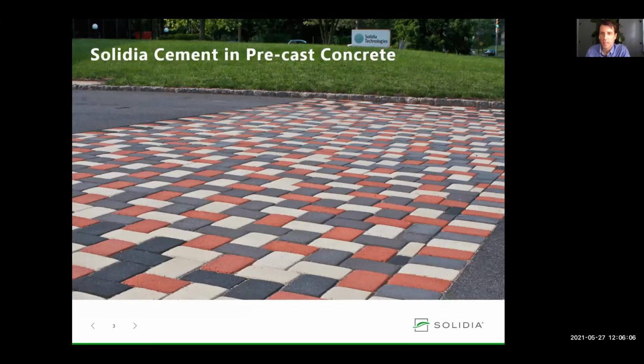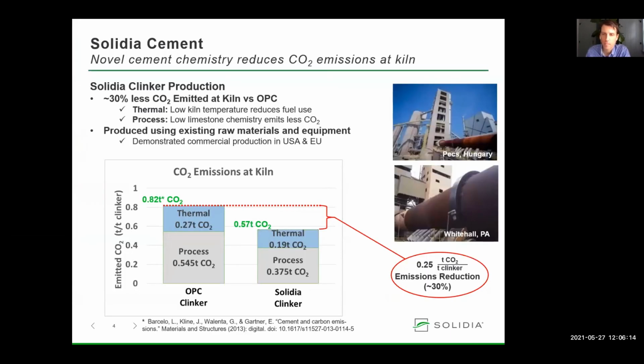Let's first take a look at Solidia cement and precast Solidia concrete. This photo shows a precast Solidia paver installation at our headquarters. Solidia cement is commercially produced both in the United States and Europe. It's produced using the same raw materials and the same equipment presently used for OPC production. The production of Solidia clinker emits about 30% less CO2 at the kiln when compared to OPC. Lower emissions are the result of the low limestone chemistry of Solidia cement, which requires lower kiln temperature, saving fuel, and less CO2 emitted from limestone calcination.